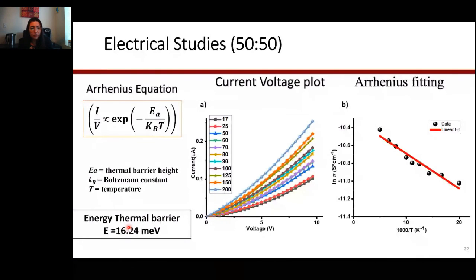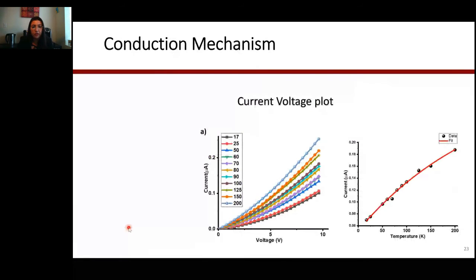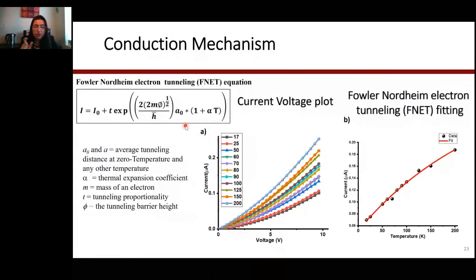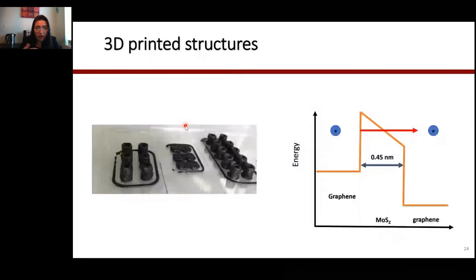And the other thing that we can do with the same type of electronic study is use the following equation, and here, this A naught is the average tunneling distance, how much distance you have between one graphene and the other. To understand this 0.45 nanometer, it's really important to determine if the electrons are hopping or tunneling through. And the data that we get here is really what is really important for us in this case.